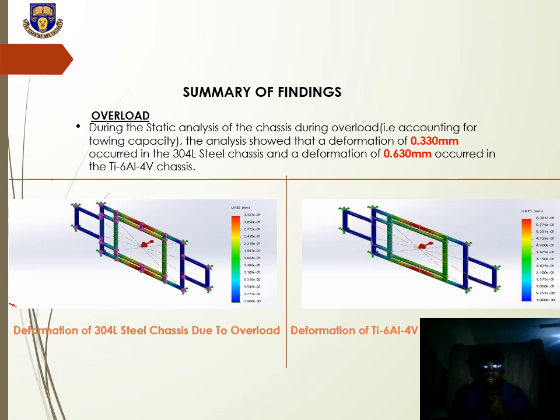Then we also did another simulation for overload. Overload refers to the towing capacity of the vehicle, and we normally add 20% of the total weight of the vehicle and the passengers to the weight that will be used on the chassis to calculate for overload. So overload determines the towing capacity of the vehicle. Under overload, it was discovered that the deformation in the 304 steel chassis was 0.330 millimeters, and the deformation in the titanium alloy chassis was 0.630 millimeters.